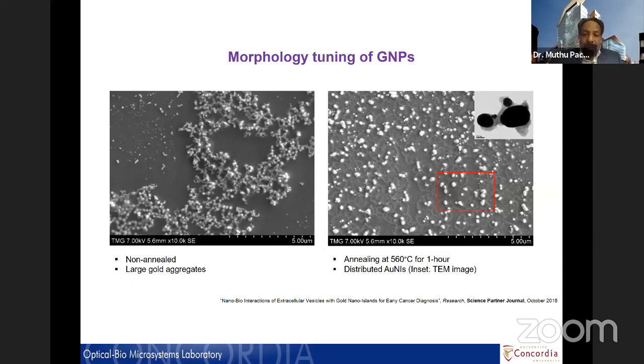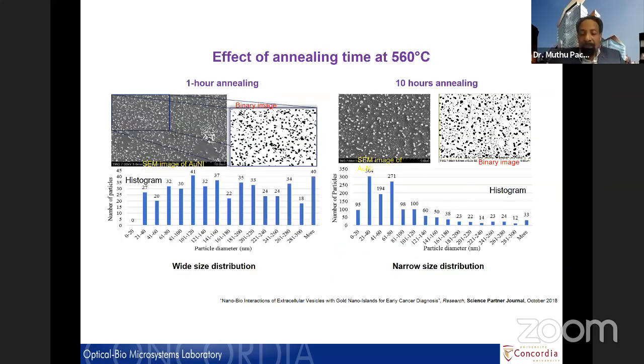These are the gold nanoparticles of different sizes, which is based on the thermal treatment, temperature, and time. One can tune the sizes, and we need a larger nano island because these exosomes are larger in size, hundreds of nanometers. So we cannot detect these larger biomolecules with the smaller nanoparticles. We need a large nano island. That's why we created this new technique of making nano islands that suit the size of the exosome. That's the key here.